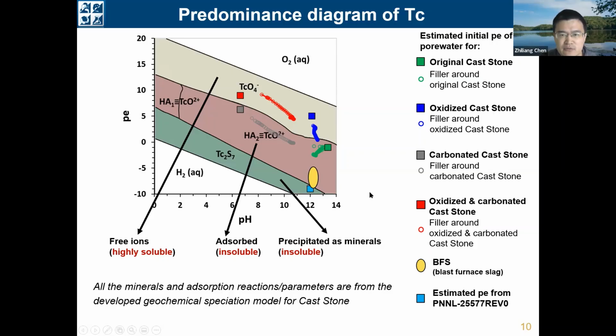So the redox state of the original Cast Stone, as indicated by this green square dot, is in the region of insoluble technetium. So that means the redox states of the original Cast Stone is capable of stabilizing technetium. However, for the oxidized Cast Stone, the redox states indicated by this blue square dot and the red square dot are in the region of highly soluble technetium. So that means the oxidation of the Cast Stone will greatly increase the mobility of the technetium.